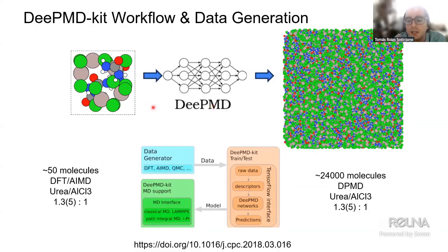We pass those trajectories, forces, and energies calculated with the AIMD through a neural network designed by the software package DeepMD to produce a potential based on those calculations that can later be translated and used in a classical molecular dynamics, meaning that we could run systems up to 24,000 molecules, which means nanometers of scale and nanoseconds of time scale, but with a very high accuracy comparable to the AIMD systems. So right now we're working on this again for the aluminum battery systems, and we are trying to reproduce first results similar to AIMD for classical MD.